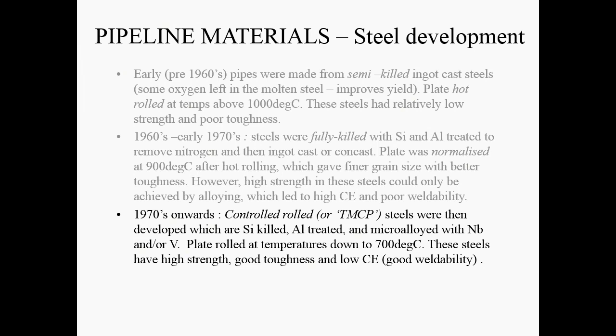So we had continuously produced material of fully killed composition, good strength, but the weldability needed to be improved. So what could we do? Well, from the 1970s, what are called controlled rolled steels were developed. Controlled rolled doesn't mean rolled at fridge temperatures, below room temperature. It means that hot rolling was over 1,000 degrees C, cold rolling is less than 1,000 degrees C. So it's cold by the molten steel terms, but not cold by normal terms.